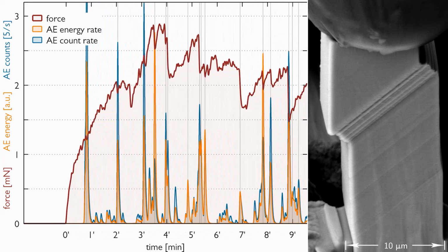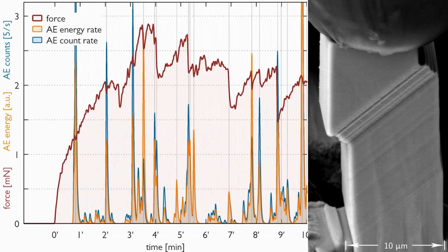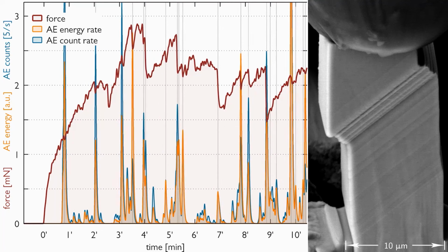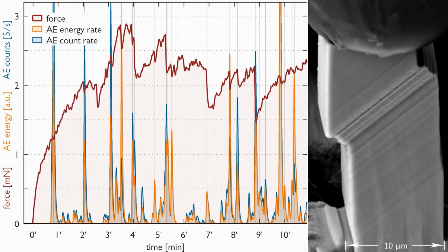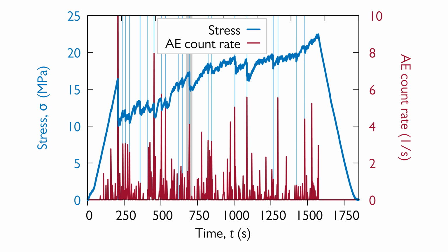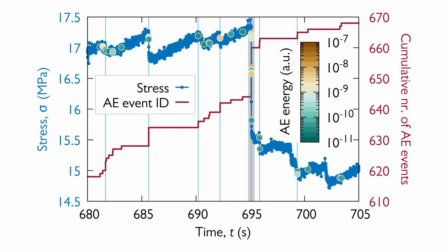It is obvious that the correlation between the appearance of slip bands, the stress bursts, and the acoustic emission activity is very robust. Let's inspect in more detail the stress drops. If we zoom the parts of the stress time curve shaded with grey colour consecutively, we can see that several acoustic emission signals correspond to the same stress drop.